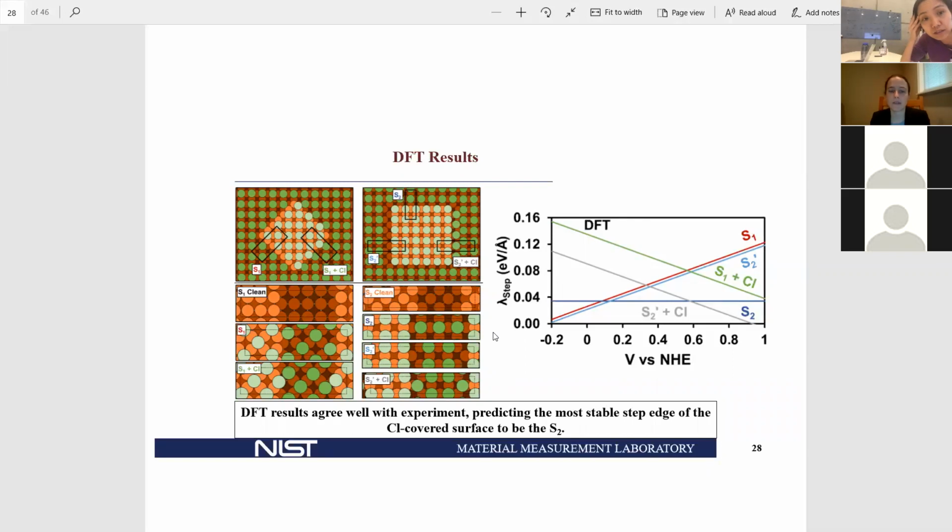Yeah, so it does dissolve at a point. It's fairly stable before that point. The exact potential, I don't know offhand, but people routinely study this surface at potentials near 0 volts versus SHE. And something that has been noted about these surfaces is frizzy steps in STM images. So basically the steps are moving back and forth, and you can see that, but it's too fast to detect on the time scales of STM. So that sort of gives you an idea of how close you are experimentally to an unstable region.